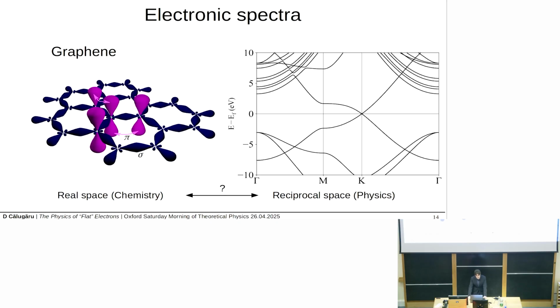If you think like a chemist, you will think about graphene in real space. You have orbitals, you have bonds, you have hybridization. But if you're a physicist, you're drawn to these spaghetti-like plots, which are in reciprocal space, right? So you introduce concepts such as Brillouin zones, dispersions, band crossing, and so on. But there seems to be some kind of a conceptual gap, right? On the left, we have localized atomic orbitals, which feel very intuitive. But on the right, we have a band structure which is completely delocalized. It's a momentum space object.